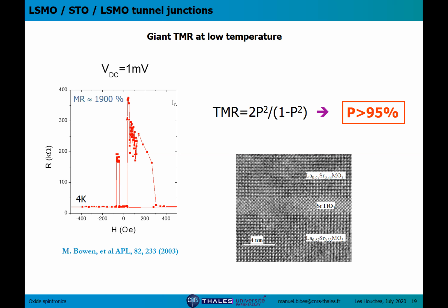You may wonder why the shape of the TMR curve is so weird. This is because we had an antiferromagnet, cobalt oxide, on top of the top electrode to induce exchange bias, a shift of the coercive field of the top electrode. And the exchange coupling was not great, so we didn't have a very nice plateau, but we were able to reach this small plateau here with a large effect.